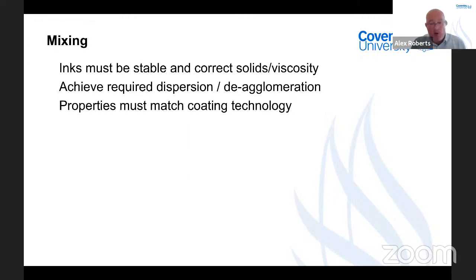The question that comes from that is how long must they be stable for? The simple answer is long enough to be able to go through the rest of the process to make your electrode. Correct solids and viscosity, these must match the coating technology that you're going to use, whether it's a drawdown coater, whether you're doing it by hand, or whether you're doing it by spray coating or from a slot die full production.